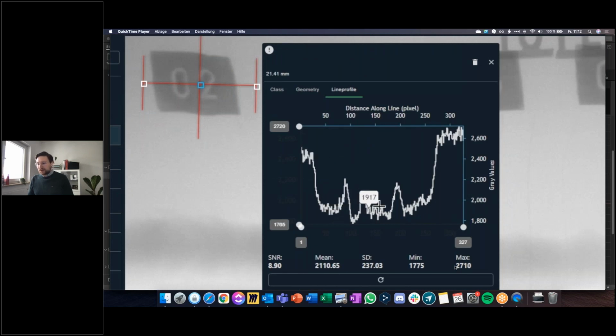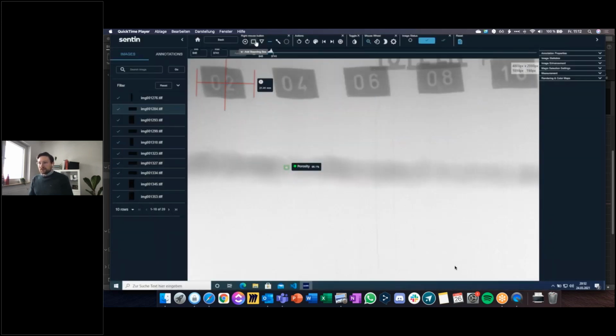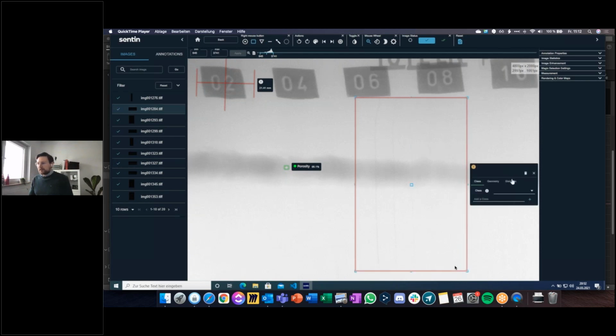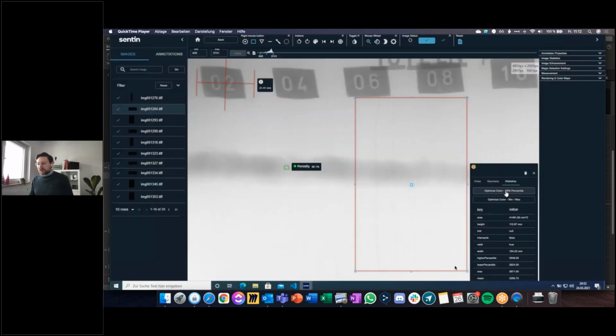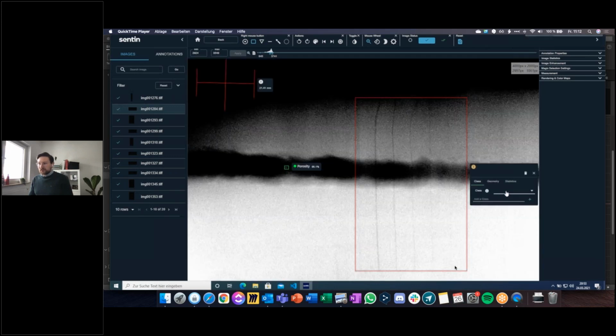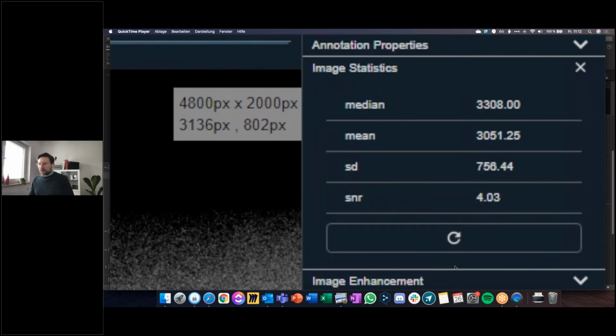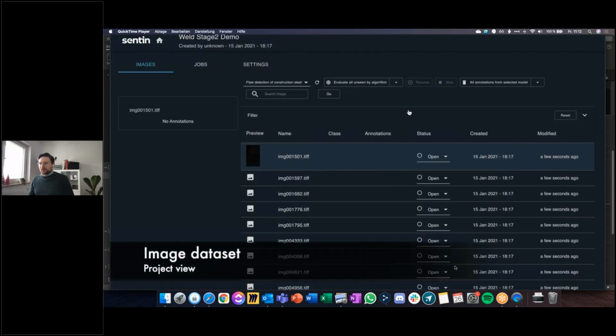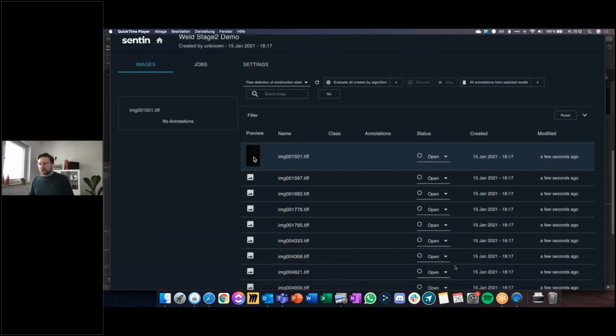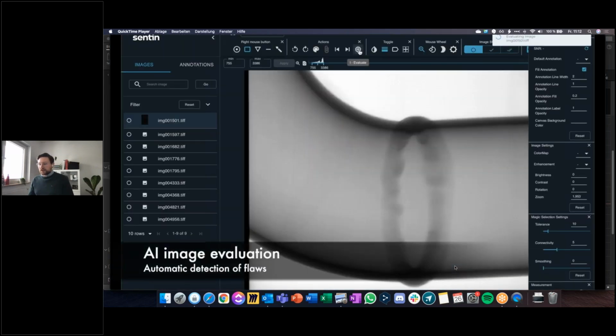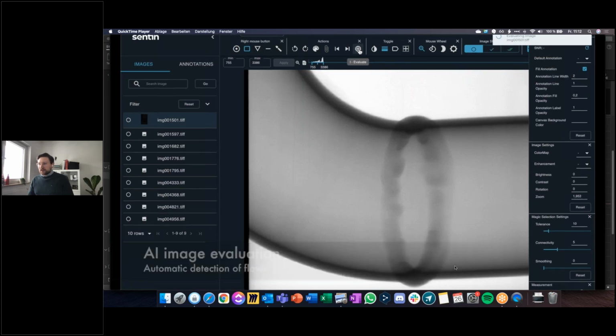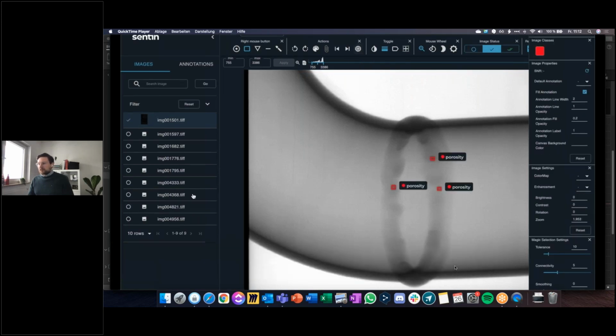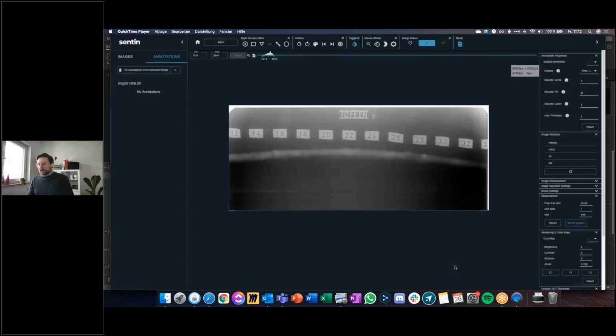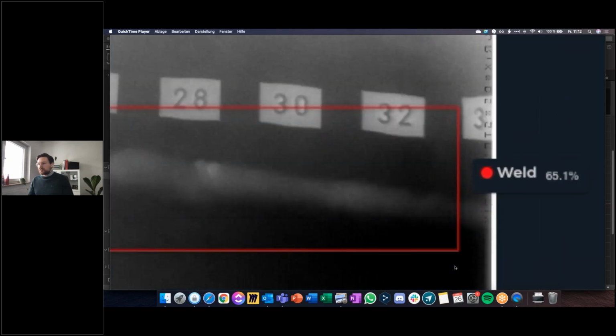This is the line profiling, where you can see the gray value distribution in a certain area. And then we have the color stretching, or contrast stretching, where you can optimize the view, examining the X-ray files for a certain window or box. On top of that, you get some image statistics on the images, and then we go into the next image and we hit the evaluate button, and this is where the AI starts evaluating the weld seam. And right here we found some porosities, and we do it on the next image as well. The computing time, by the way, is around 2 seconds on a GPU.